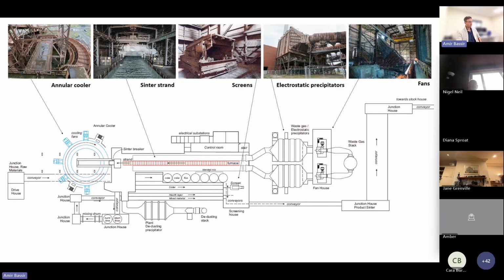Upon reaching the end of the strand, it drops through a sinter breaker into this annular cooler, where for about 25 minutes it's cooled down. In the sintering process itself, there's a great big fan house at the end, and the suction fans draw air down through the sinter bed, which partially melts and fuses the material to create the sinter. Once the sinter is cooled, it's then crushed and screened to the required size, and any dust is returned back into the process to be reused, and the sinter passes through all the screening plants, goes along the conveyor out to the junction houses and onto the stock house.